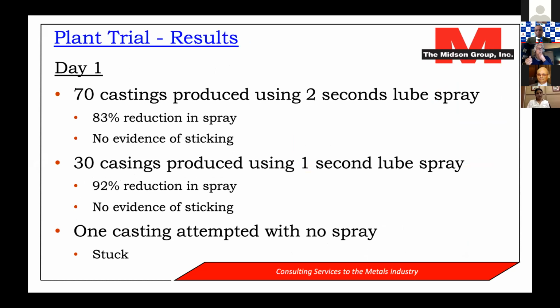So here are the results of the plant trial. On day one for the coated die, initially we went from 12 seconds with the uncoated die to 2 seconds with the coated die. That's an 83% reduction in spray, and 70 castings were produced with no evidence of sticking. So then they went down to 1 second of spray, which is about the minimum amount of spray that they could run with their equipment. That's a 92% reduction in spray from the 12-second use previously, and they produced 30 castings with no evidence of sticking. So then they went to no spray, and they turned the spray off, and the first casting stuck.